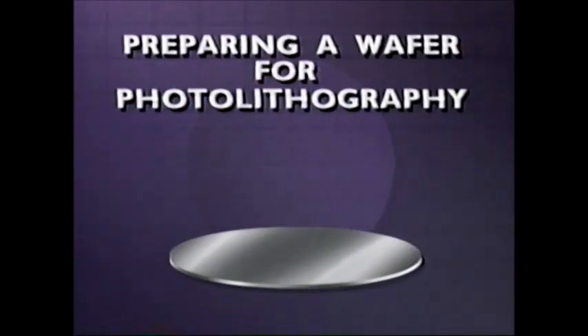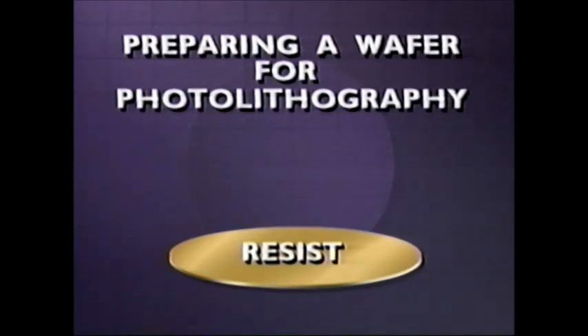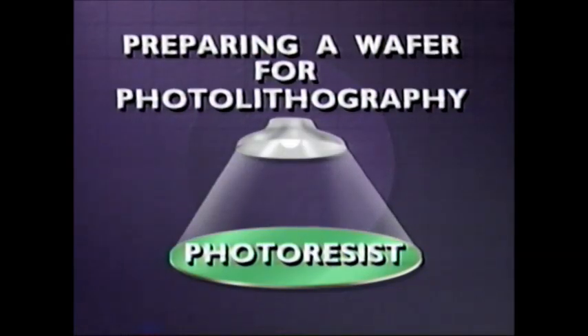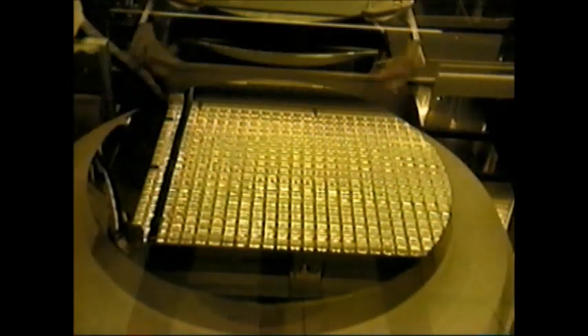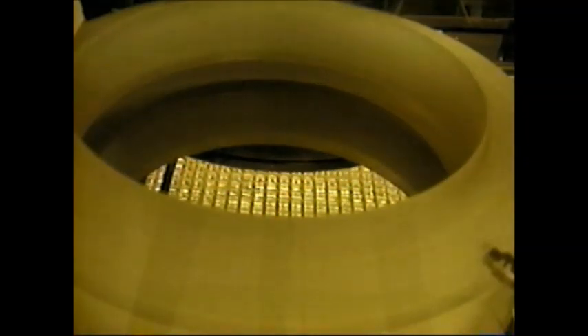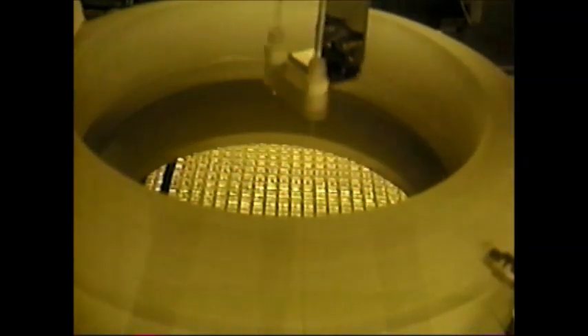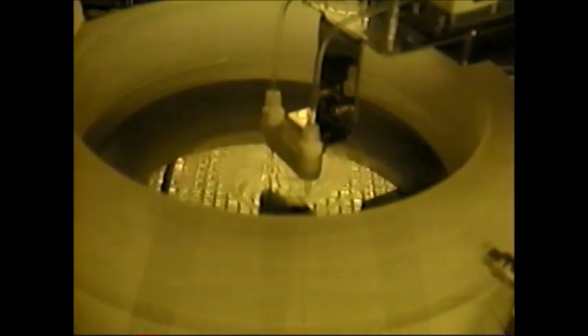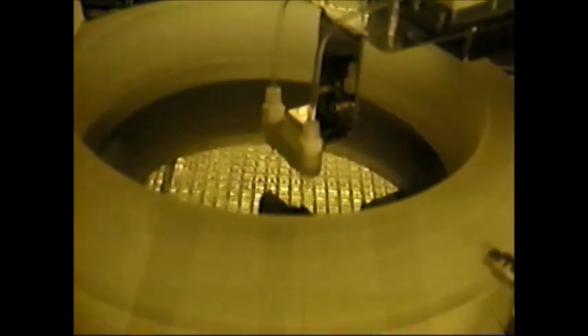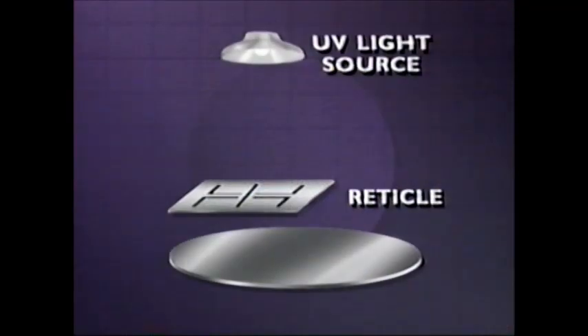To prepare a wafer for photolithography, its surface is coated with a uniform layer of resist, so called because it resists the plasma etching. When light is used to expose the resist, it is called photoresist. Photoresist is spun onto a wafer at high speed to form a uniform layer. Photoresist material, which is carbon-based, is particularly hardy when used with gas plasma during the dry etching process.